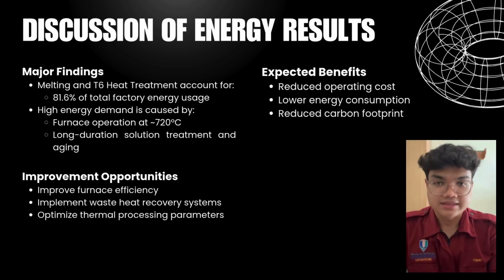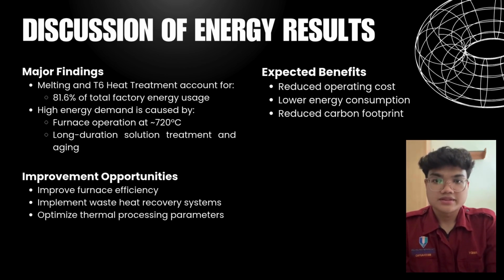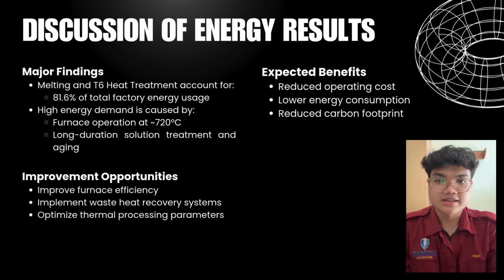Based on the energy analysis, melting and refining together with T6 heat treatment account for approximately 81.6% of total energy consumption. The main reason is that these processes require prolonged operation at high temperatures. For example, the aluminium must be heated to around 720 degrees Celsius before casting, while the T6 heat treatment involves solution heat treatment and artificial aging over several hours. Therefore, improving furnace efficiency and implementing heat recovery system can significantly reduce energy consumption. These improvements would lower operating costs and reduce the environmental impact of the manufacturing process.